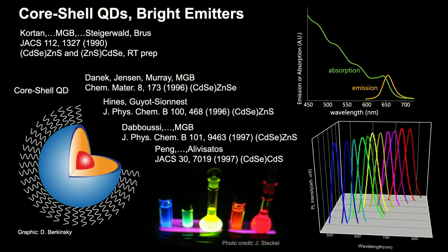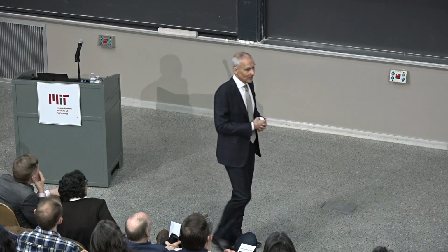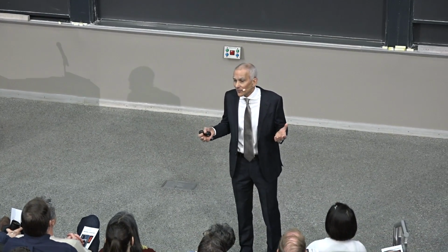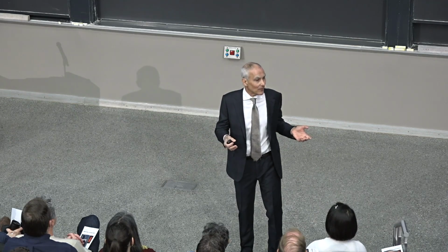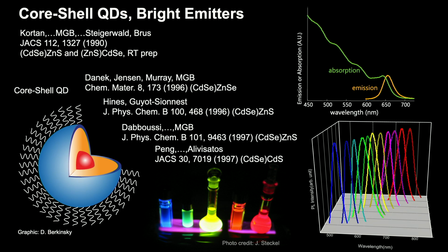An important step was also to realize, and this is something that Mike Steigerwald and Lou Brus had realized early with their own synthesis, that the surface was still chemically active. So you could grow on top of it a shell of a different material. And so realizing that this quantum yield issue, this 20%, which seemed pretty bright to us but wasn't 100%, which is really what we wanted, was because the surface was right there, and there were defects on the surface, and that allowed us to lose the energy of that electron through interaction with the surface. So if we could build a really nice shell that could contain that electron in the middle without it seeing the environment, that could be a way.